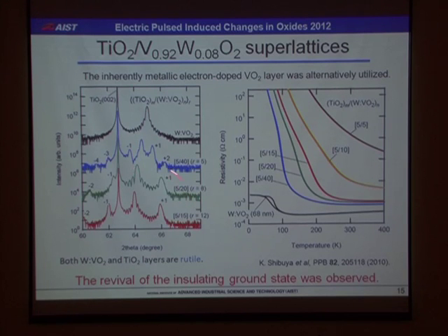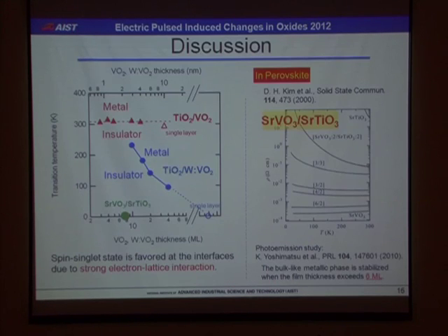Here, XRD is much better because both TiO2 and electron doped VO2 have a rutile structure at room temperature. And actually, the electron doped VO2 single layer shows a metallic ground state. All these superlattices show an insulating ground state. So this is a short summary of these superlattices. And the transition temperature is plotted as a function of VO2 thickness. This is the case of TiO2 with non-doped VO2 and TiO2 with electron doped VO2. And the transition temperature is almost constant due to the very robust vanadium dimerization.